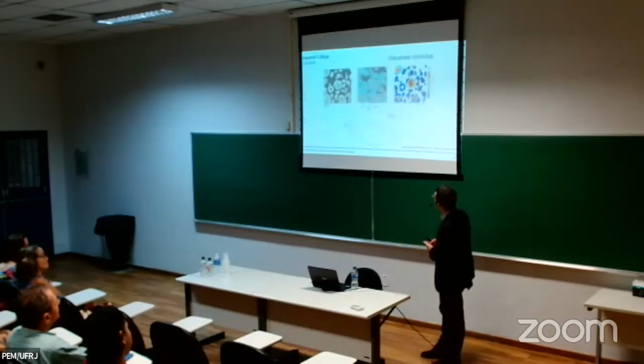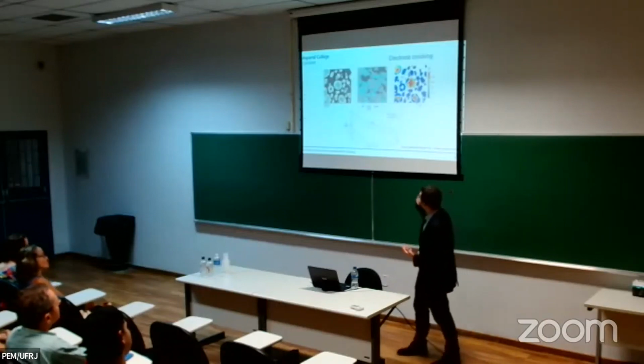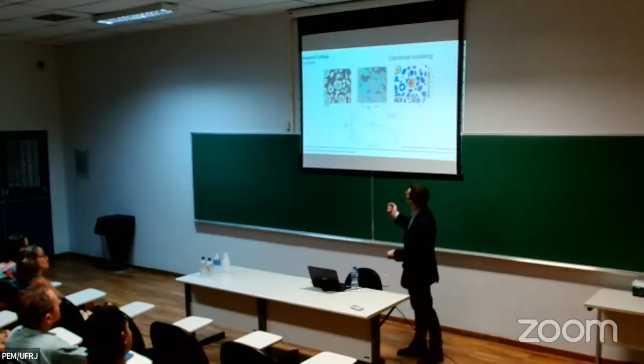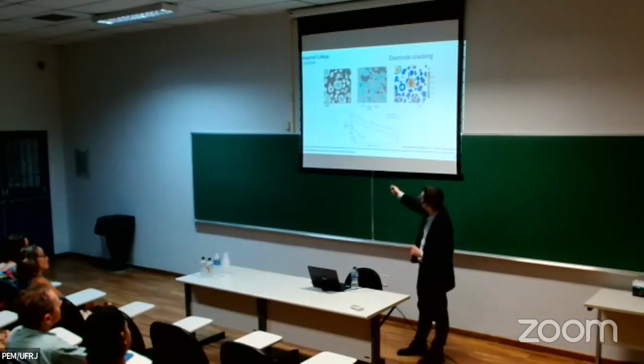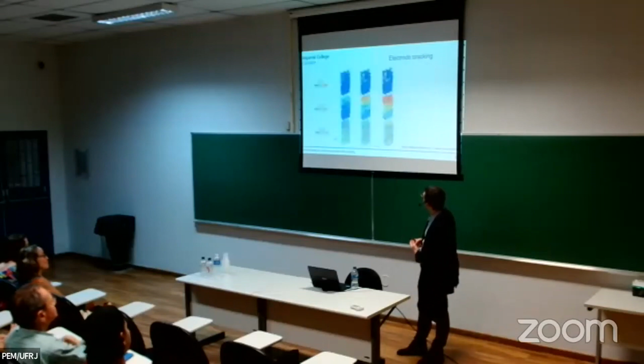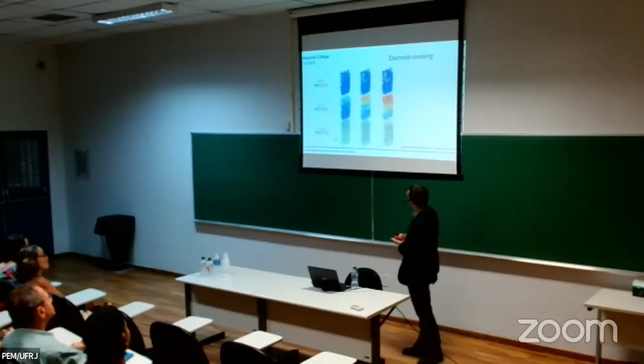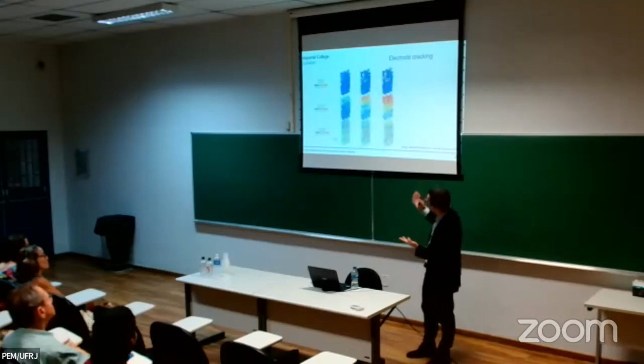And computers today are sufficient to do this. Again, we couple this with the imaging facility, so we can do X-ray scans of those electrodes. Then we do the segmentation, so we can determine the different phases, the carbon binder and the particles, and then we do our finite element analysis. And we do this in 3D, encompassing dozens of particles. And these are some representative results.